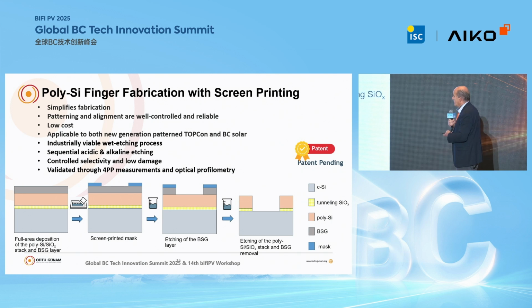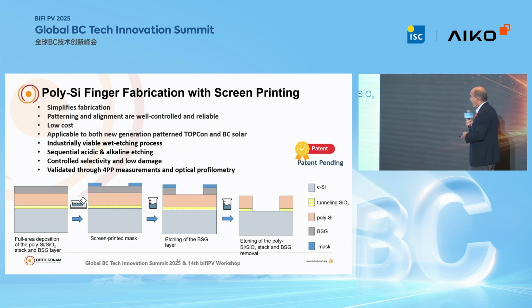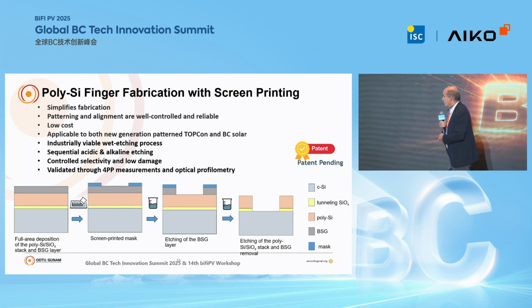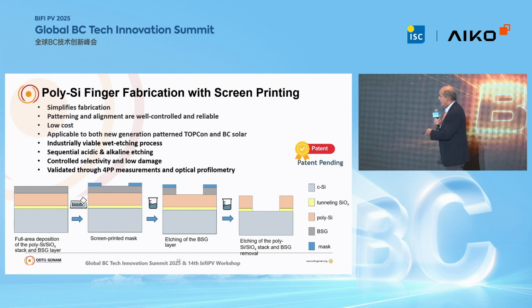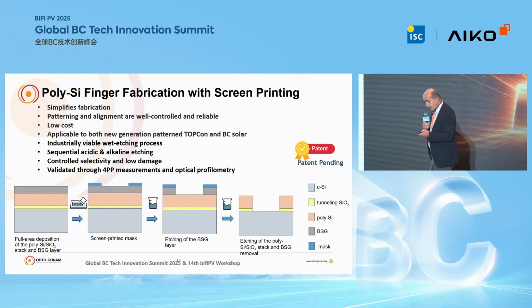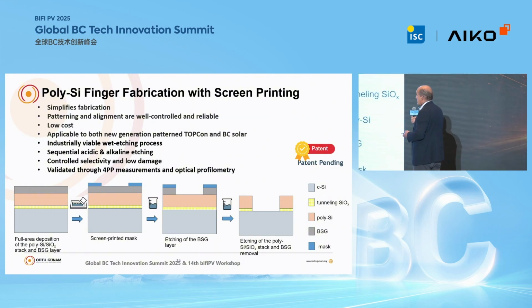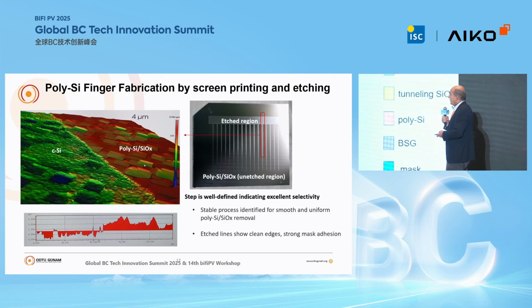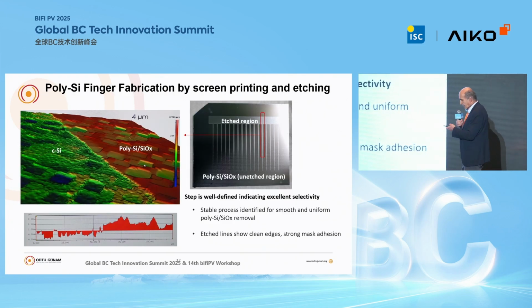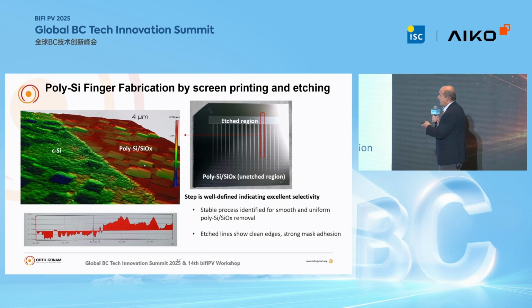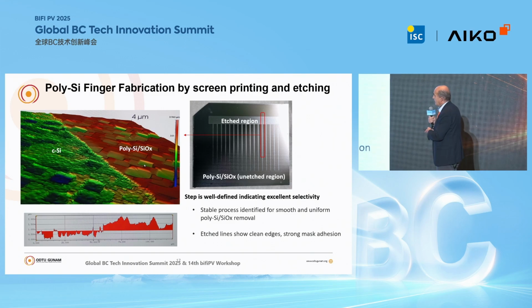So this is quite controllable technique, and you can, of course, test this, monitor this process using 4-point probe or ellipsometer or optical technique. So it's quite viable and easy technique. And here you see that very sharp edges can be created, and well-defined fingers can be fabricated using screen printing.